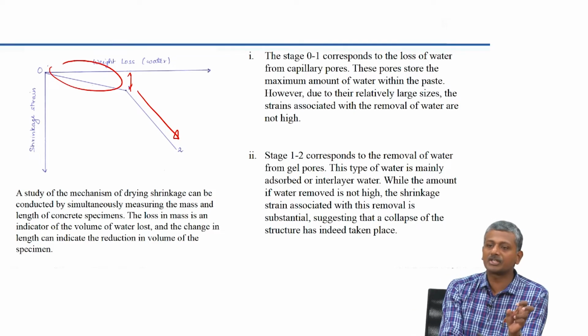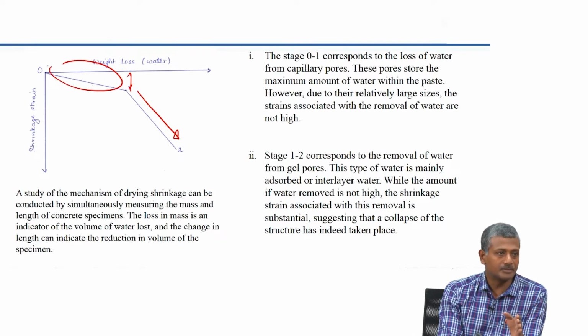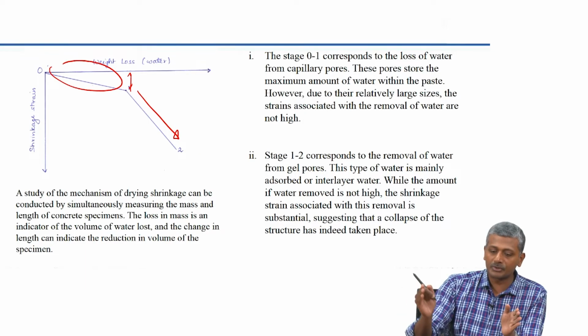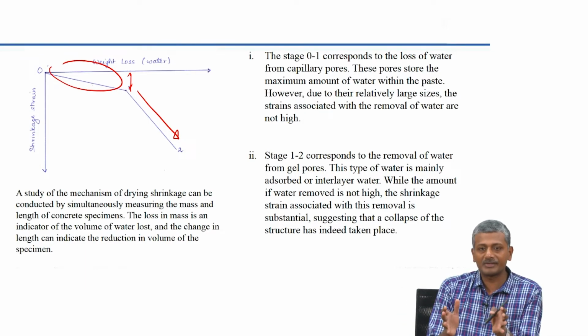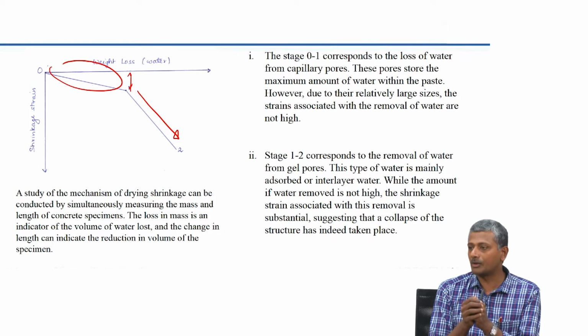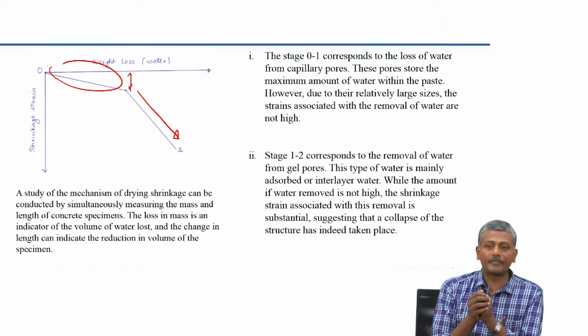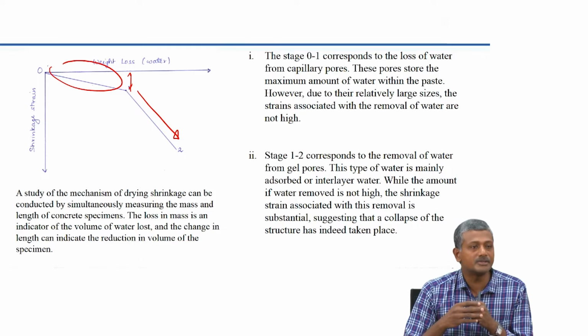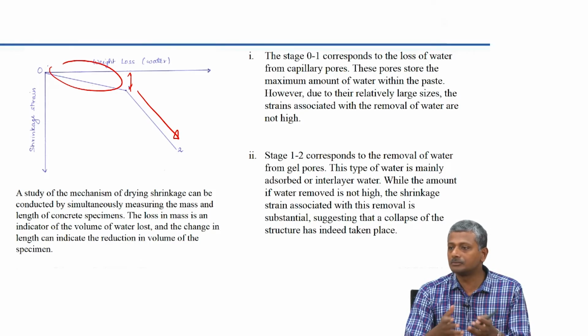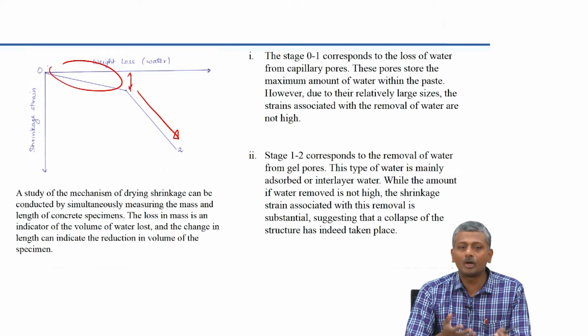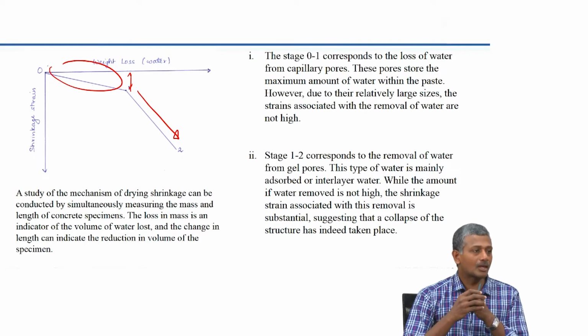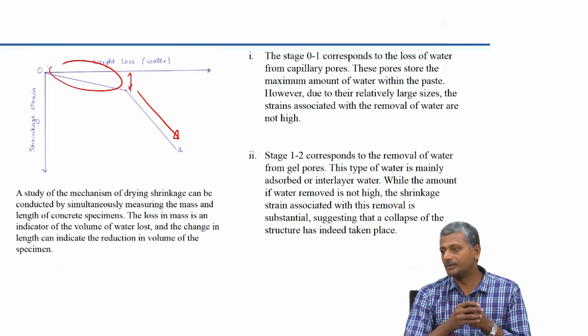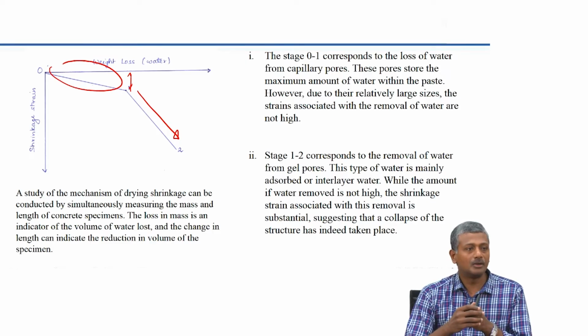So, generally shrinkage can be looked at as a two-phase mechanism. The first phase is where water goes out of the coarser pores and does not really produce much shrinkage. The second phase is when you start pulling out water from the finer pores, which produces a lot of shrinkage but a lesser amount of weight loss. So, when you look at shrinkage related experiments that are described in papers, if people are only studying shrinkage for 2 weeks or 3 weeks, they may not even be reaching a significant part of the second phase. Because of that, when you conduct shrinkage experiments, you need to do it for at least 6 months to 1 year to get any realistic assessment of shrinkage.